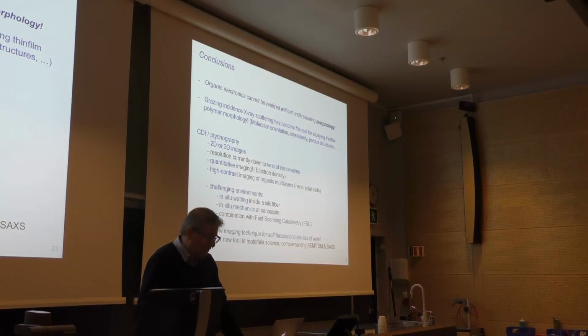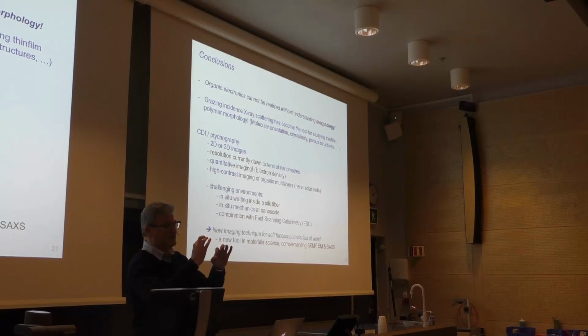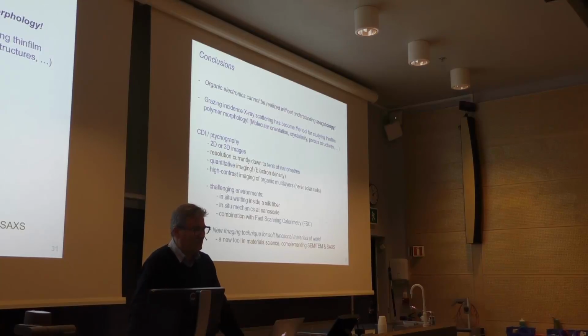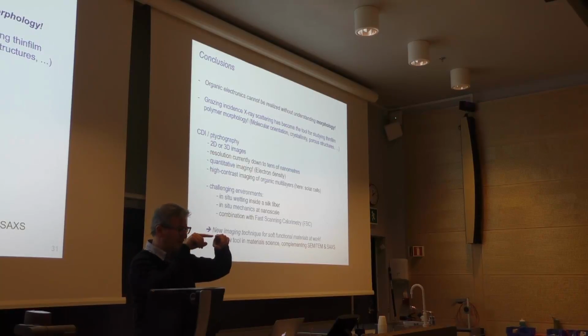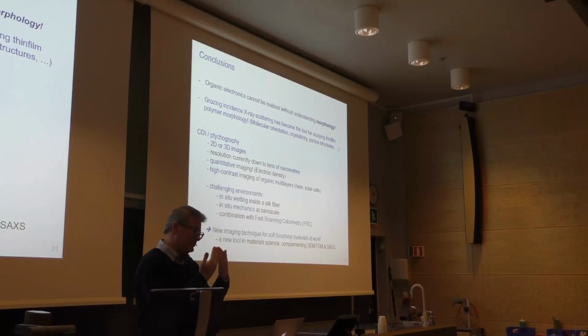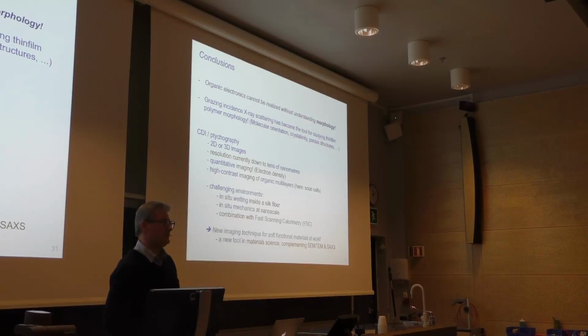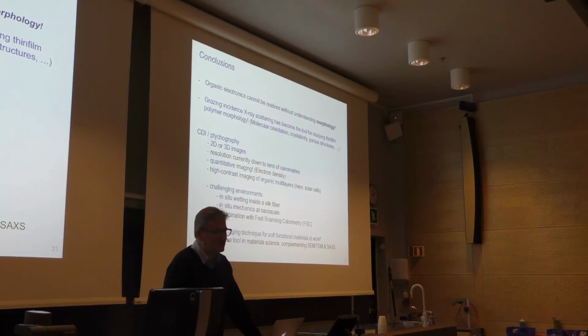But people are also finding ways of circumventing this, so that if you are able to prepare a series of identical copies of your material, then one can in the future use the so-called free electron lasers that are coming up in Stanford and Hamburg and other places, where one is doing single-shot diffraction experiments, meaning that you expose your sample to one shot, and then the sample is gone, it's burnt away, but just in the fraction of a second before the sample disintegrates, you have already gotten the diffraction signal that you need, right? People have already published some works on the dynamics of, I think, some membrane proteins studied using this technique.